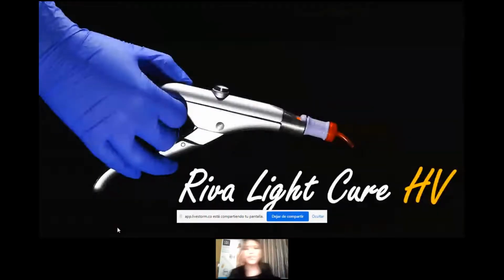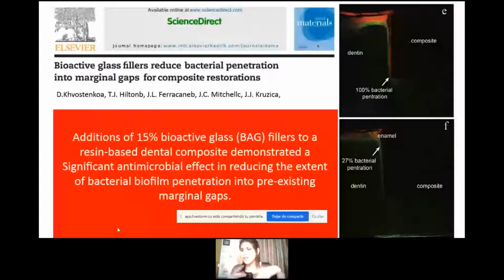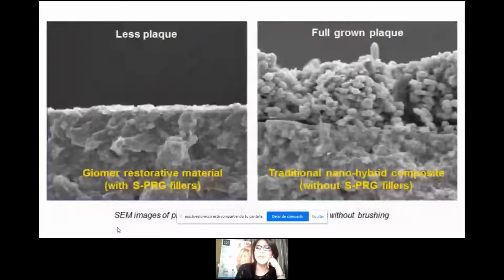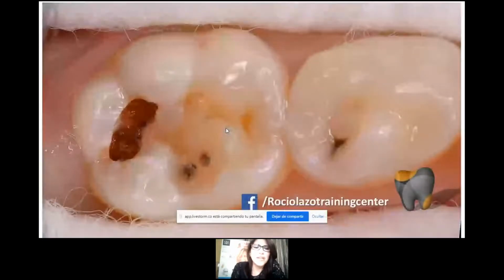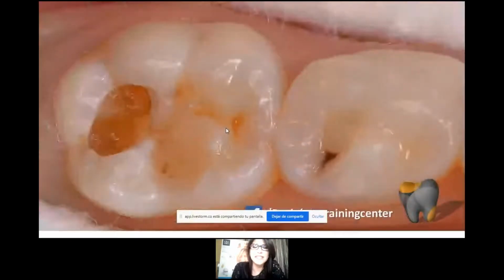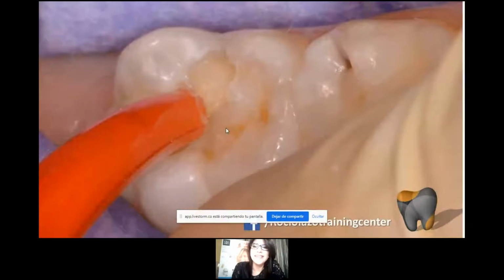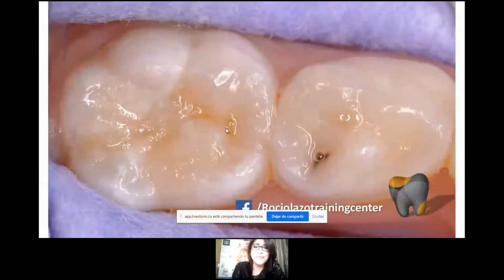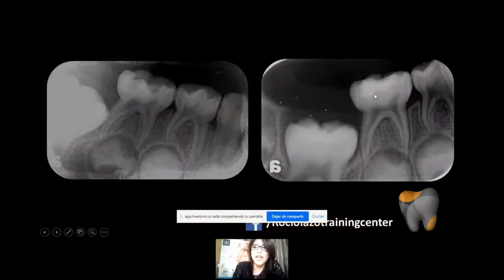Okay, so here we have Riva Light Cure High Viscosity, okay? If you have big cavities, I prefer to use the high viscosity because it will resist the occlusion forces more. And we're going to have good results with less plaque growth. This is a strontium modified glass ionomer with resins, okay? And look here, we remove the infected dentin, we have the affected dentin, and we apply the Riva Light Cure High Viscosity. Look here, the aesthetic is so great. If you compare the x-rays, good sealing.